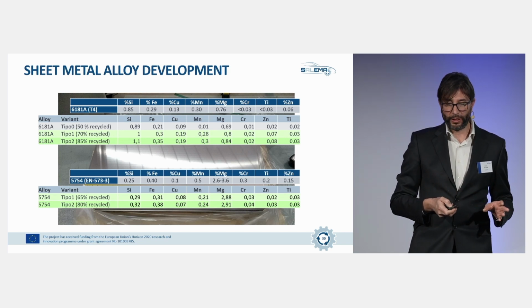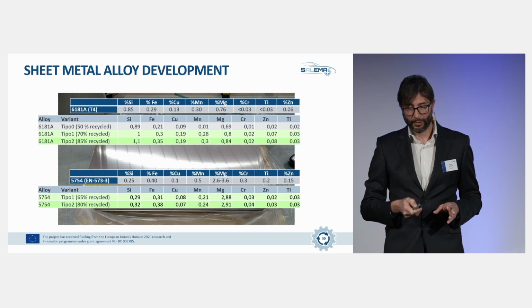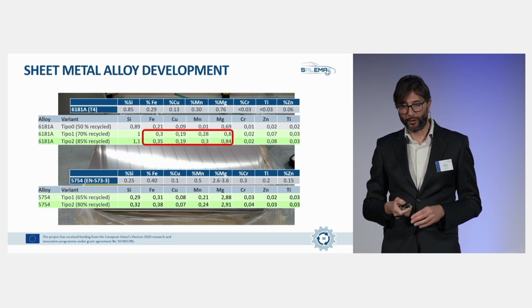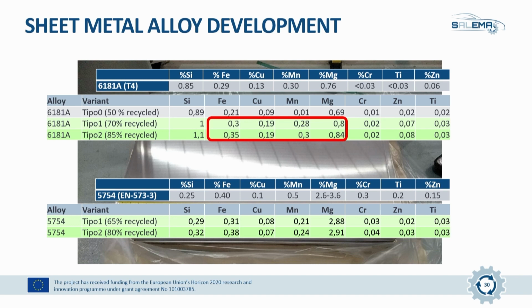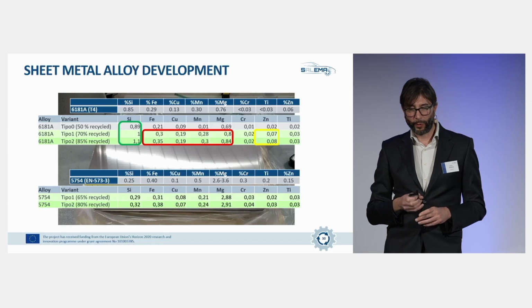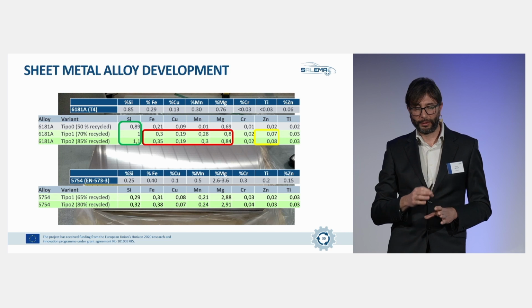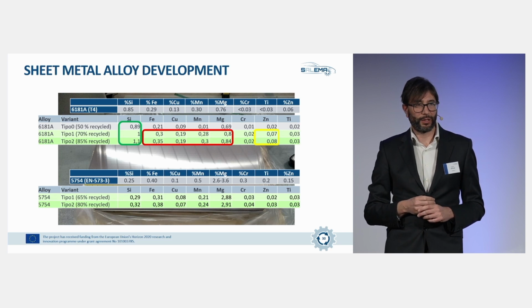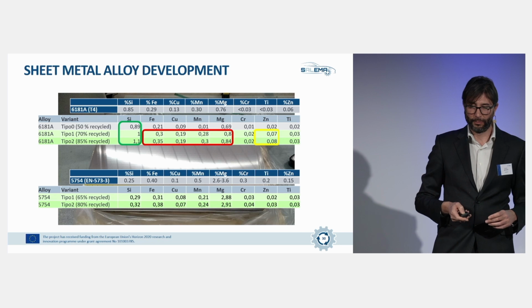Due to this increment in recycled content, it was necessary to also increase the level of impurities, mainly iron, copper, manganese, magnesium, but also we increased a little bit silicon on the 6181 and zinc, in order to allow this higher amount of recycled content. In the 5754, only iron was increased in the 80% recycled material.